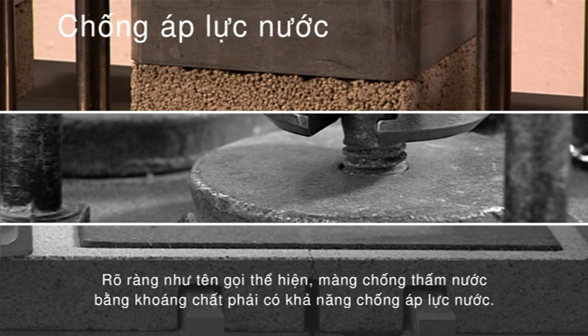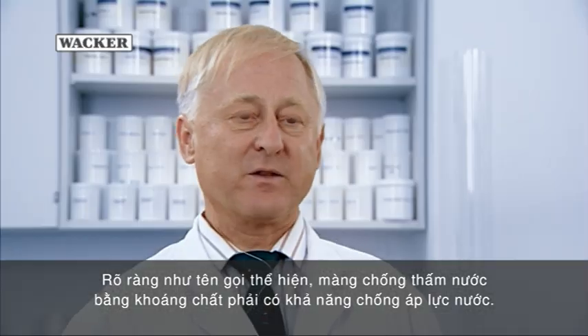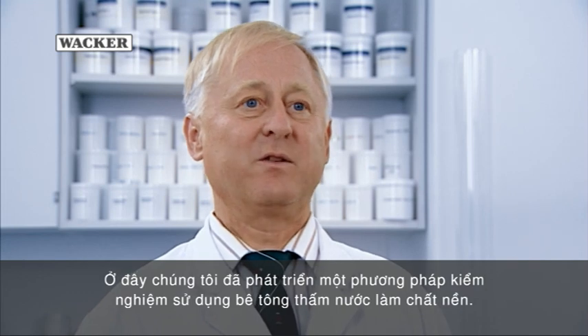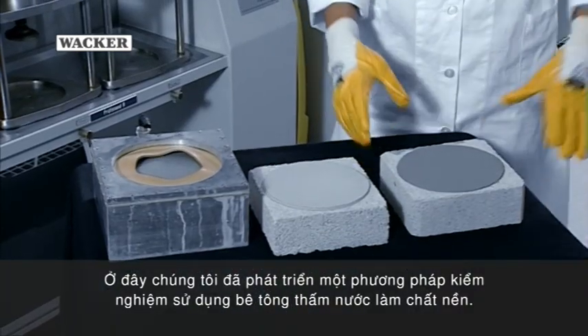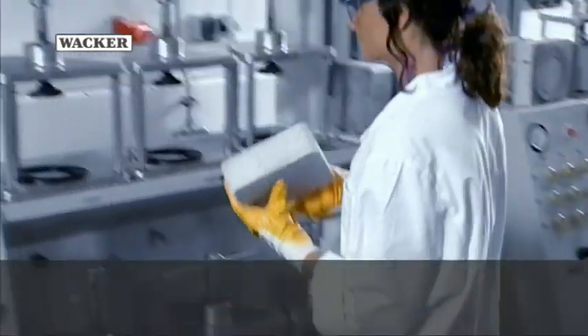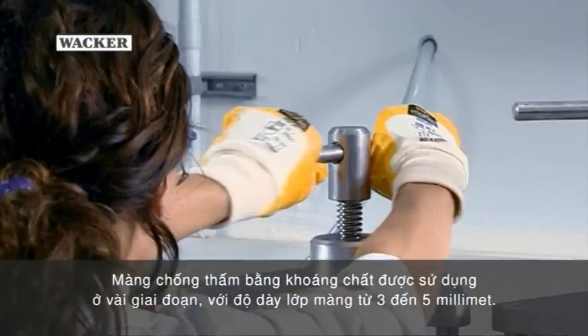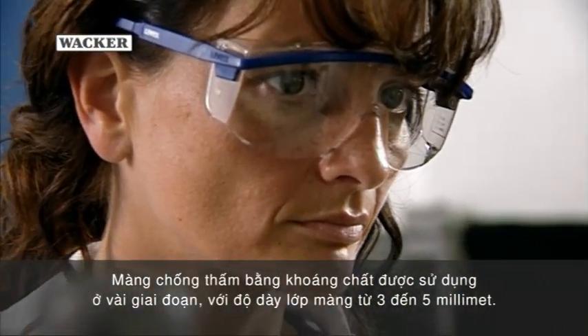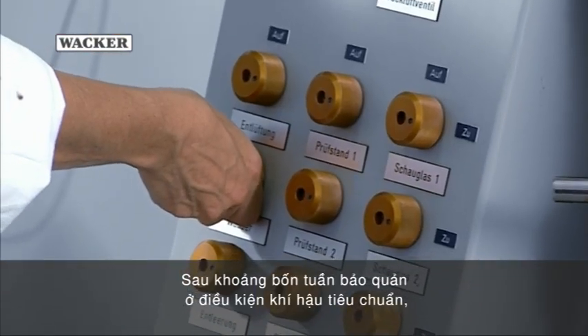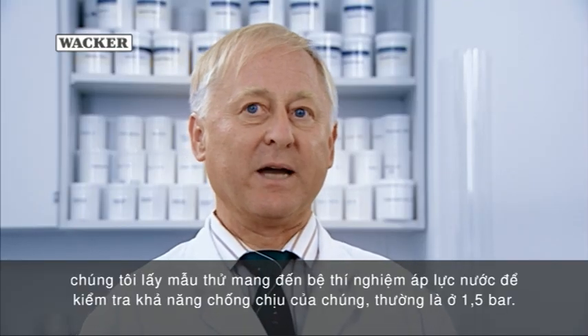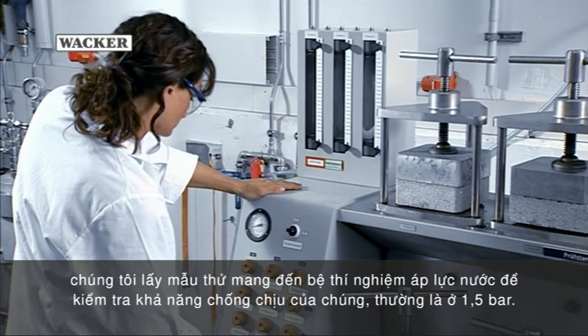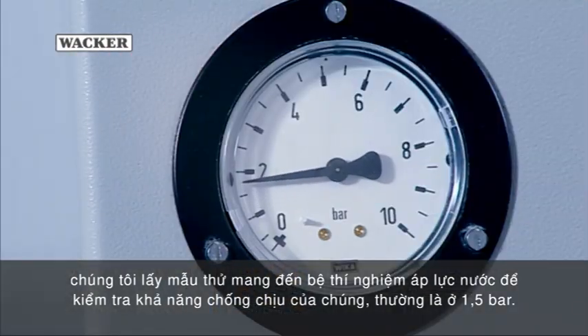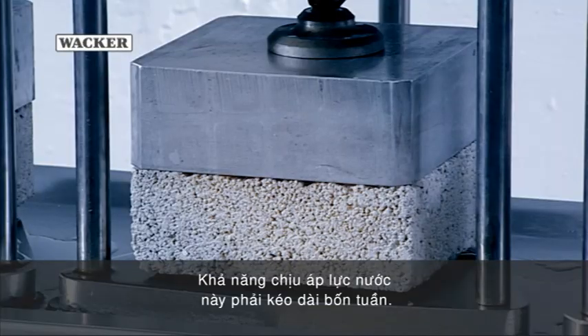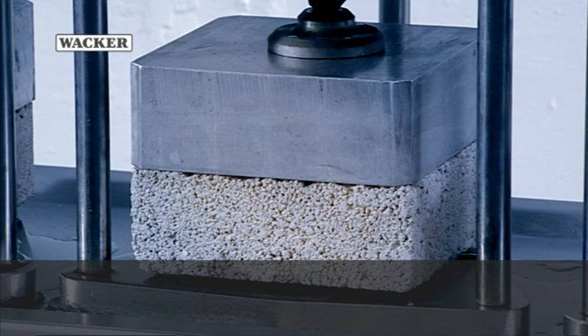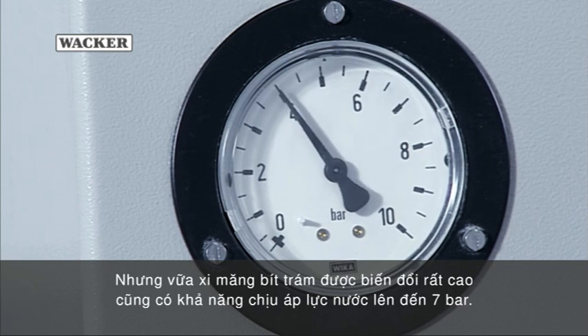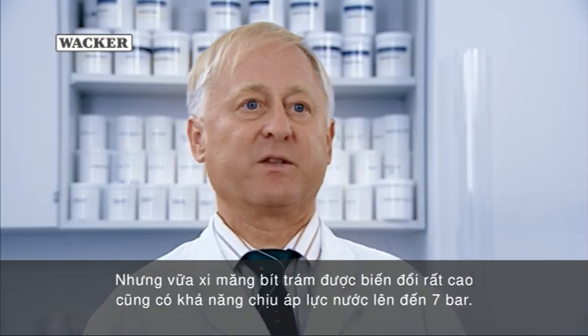As is clear from the name, a sealing slurry should be water pressure resistant. Here, we've developed a test method using a water-permeable concrete as substrate. The sealing slurry is applied in several stages, with a layer thickness of 3 to 5 millimeters. After roughly 4 weeks of standard climate storage, we take these test specimens to the water pressure rig to test their resistance, generally at 1.5 bar. This water pressure resistance has to last 4 weeks. But very highly modified sealing slurries are also capable of resisting water pressure up to 7 bar.